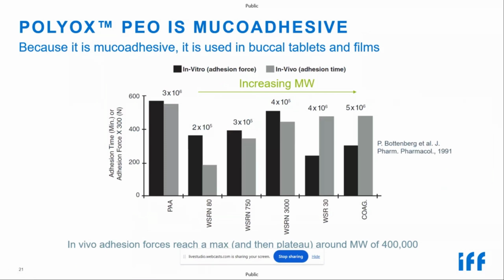The data on the graph shown here is adhesion levels of different grades of POLYOX PEO using two different methods, an in vitro method in black and an in vivo method shown in gray. This is an article that was published back in 1991. The article partially highlighted the drawbacks of using an in vitro test method and showed the benefits of using an in vivo test method. So I'm going to focus on the in vivo data because that's more relevant than the in vitro data.